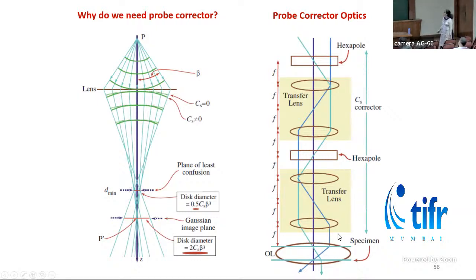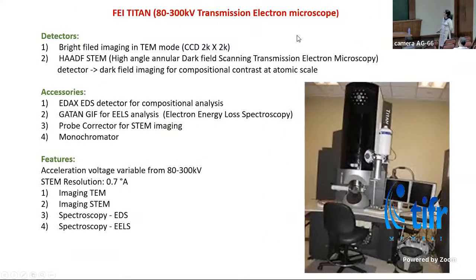But then what is the solution to that? The solution is we can add probe corrector optics in the column, which are a couple of lenses more, which try to focus the beam to a point mode, a much finer beam. So we have a Titan machine which has this probe corrector. So this is the Titan TEM, which has a 2K by 2K CCD for bright field imaging. It has a high angle annular detector for STEM imaging, and it has a probe corrector. That's why its resolution is 0.7 angstrom, and it also has EDS for elemental detection.